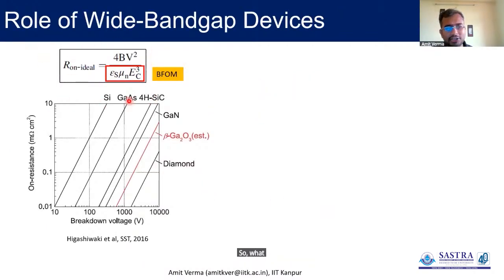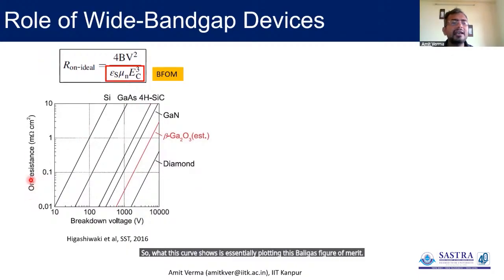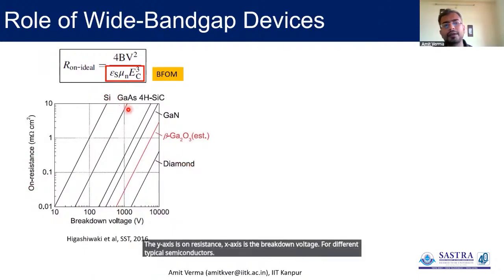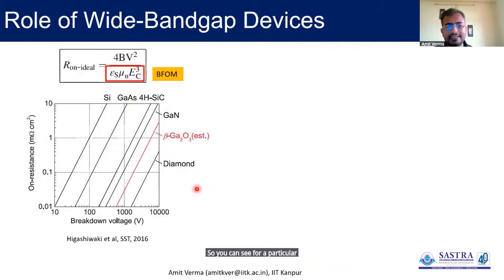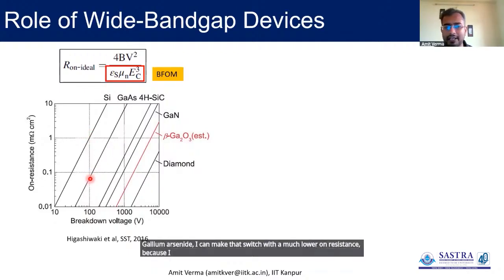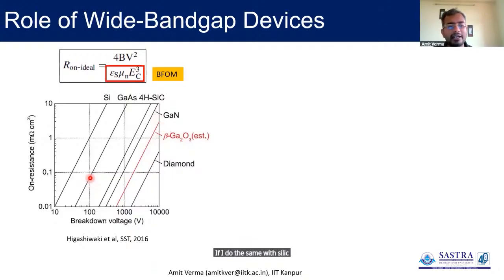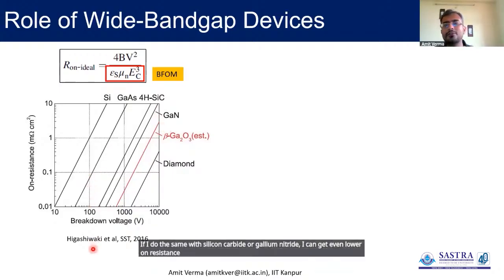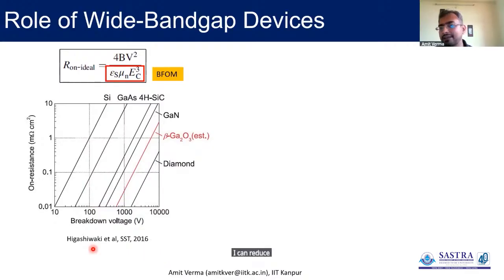So how does the trade-off work out then? What this curve shows is essentially a plot of Baliga's figure of merit. The y-axis is on-resistance, and the x-axis is the breakdown voltage for different typical semiconductors. Silicon, of course, is used, but then there are many wide bandgap and ultra wide bandgap semiconductors. So you can see for a particular application, let's say I want to make a 100-volt switch, compared to silicon, with gallium arsenide, I can make that switch with a much lower on-resistance because I can dope it heavily. If I do the same with silicon carbide or gallium nitride, I can get even lower on-resistance. As on-resistance goes down, I can reduce my power dissipation. So essentially the switching efficiency goes up. That is what I was mentioning, small improvements in switching efficiencies.